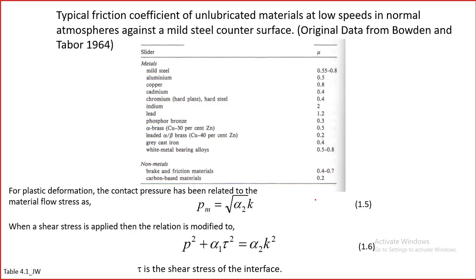Now we will see some of the data. The typical friction coefficient of unlubricated material, so dry sliding at low speeds in normal atmosphere, against a mild steel counterface. The counter surface has to be always defined, because friction as well as wear is a two material property. It is not a single material property. So you must always report the counter surface and the atmosphere. Another thing you should report is temperature. If it is not reported, we assume it is room temperature.